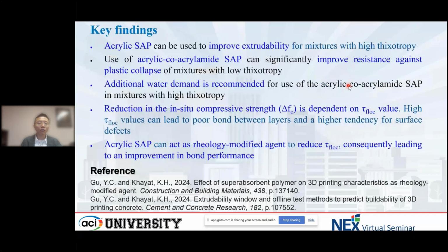And so overall, we have these key findings based on our research. The acrylic SAP, which we call SAP1, and the acrylic-acrylamide SAP, which we call SAP2 here, can be used to improve the extrudability. The acrylic-acrylamide SAP can be used for mixtures made with low thixotropy to improve the resistance against plastic collapse. Additional water is recommended for this type of SAP if we use it in a mixture made with high thixotropy.